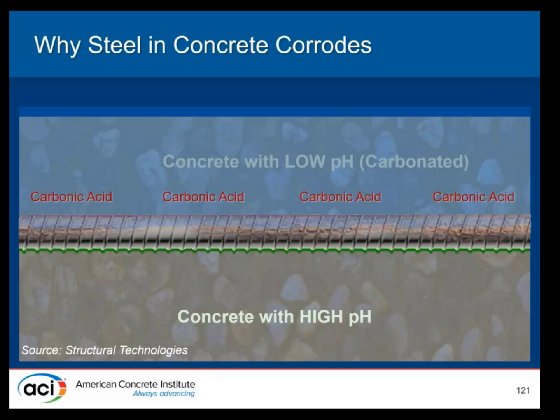In a normal environment, it's a very slow process, and it typically will take 25 years for carbonation to reach reinforcing steel that's 1 inch of cover. However, situations where there's a high CO2 environment, highway tunnels, industrial facilities, that concrete may carbonate faster. Now, the other thing that happens is obviously chlorides, water, and oxygen penetrate into the concrete as well, and the chlorides will act to destroy our passivating film as well. So the time to corrosion is a function of the steel cover depth and the concrete quality.